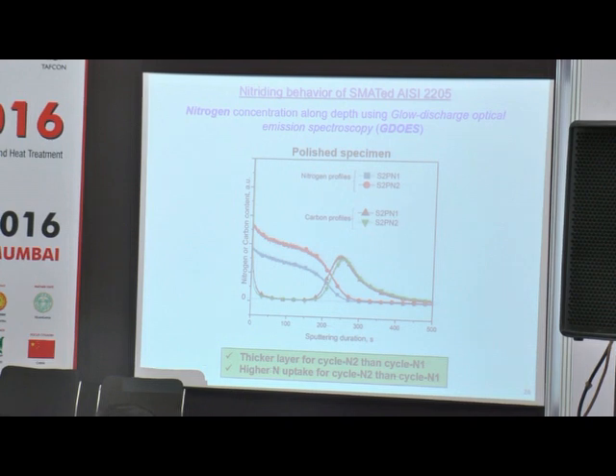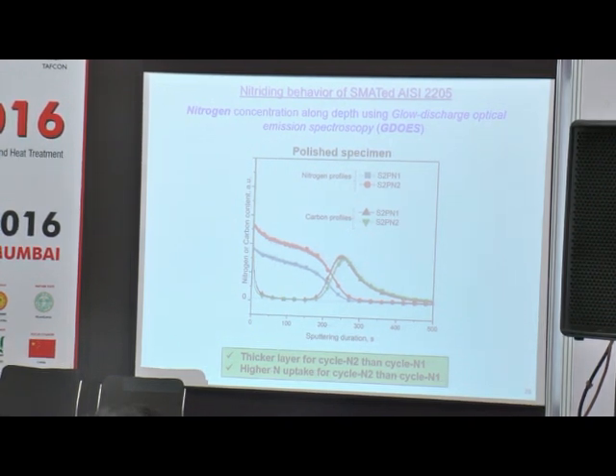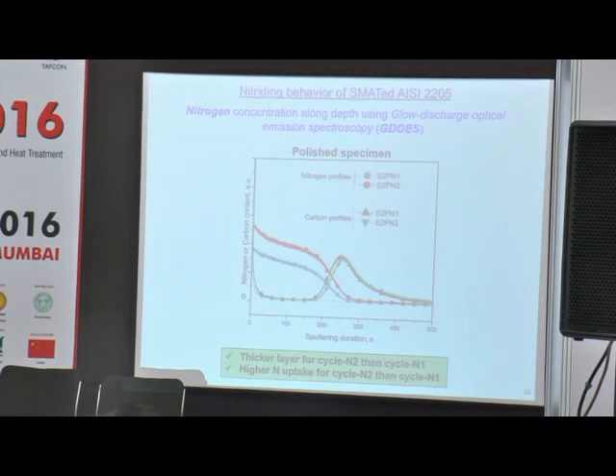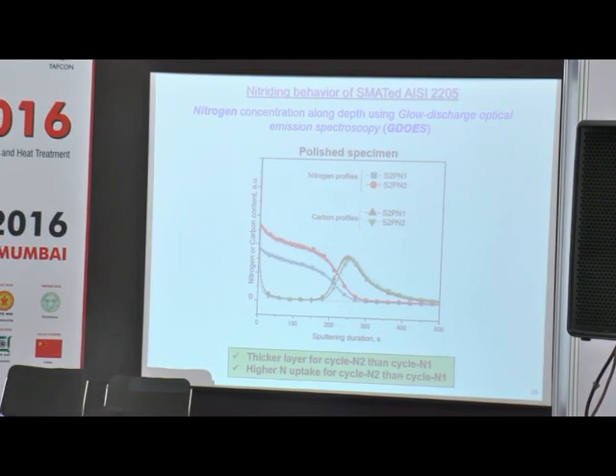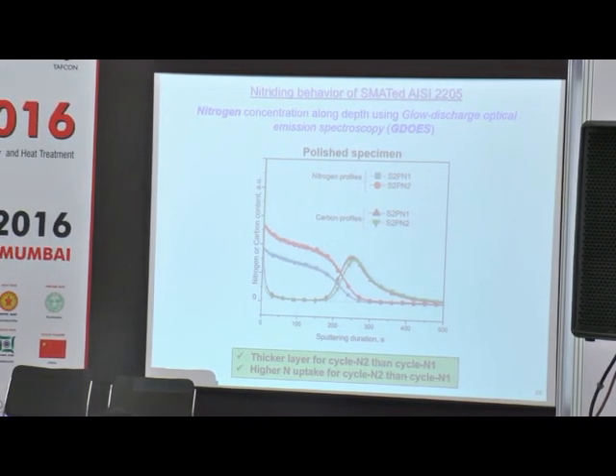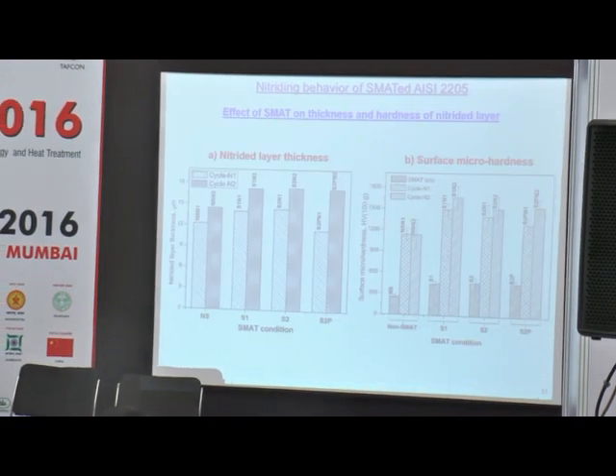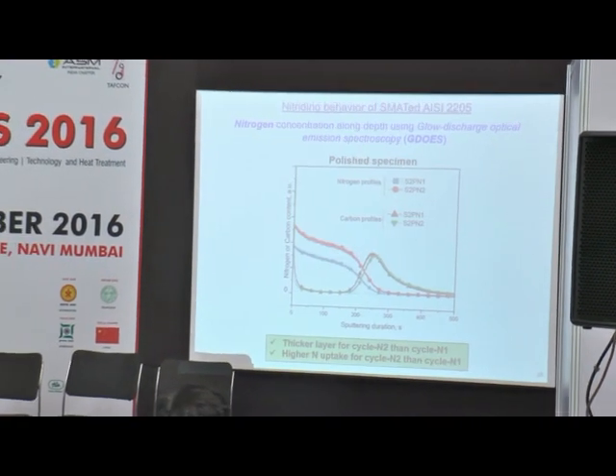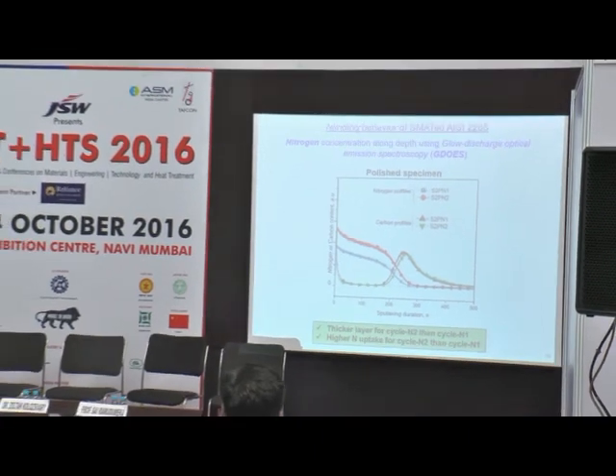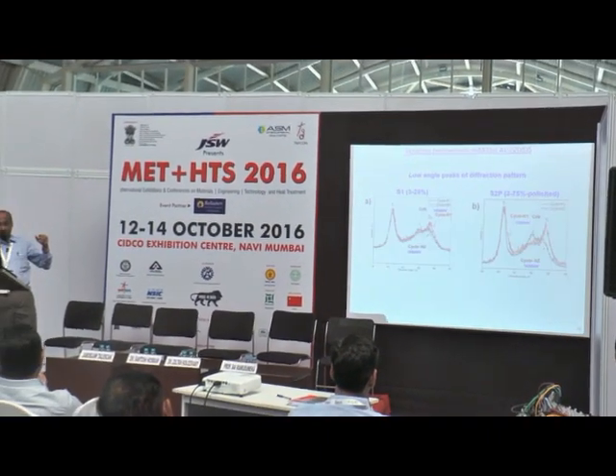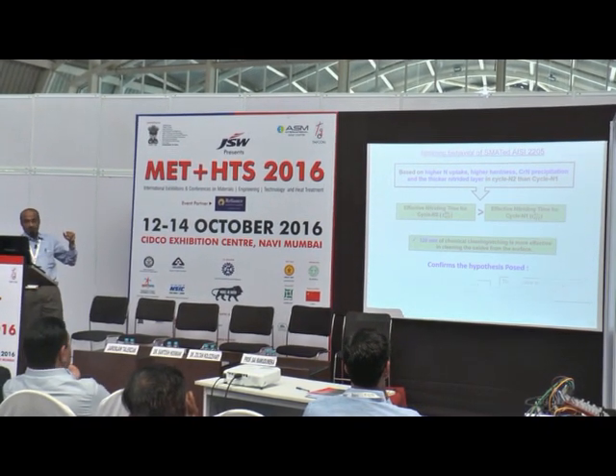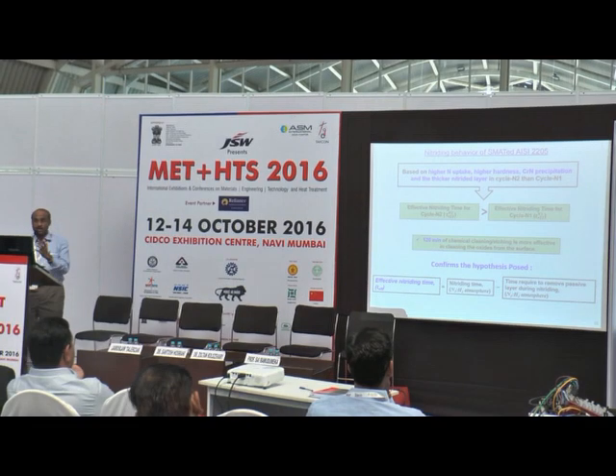The GDOES gives the nitrogen concentration depth profile. You can see that the red one is the N2 cycle. That is a higher sputter clean duration. So the higher the sputter clean duration, I got the deeper case depth. Another thing is that you got a higher surface nitrogen content. So all those results confirm that we have the influence of sputter duration on the plasma nitriding duration.